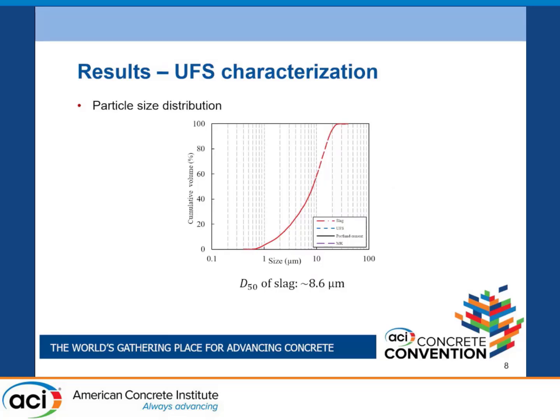Now I want to present the results for UFS characterization. For the slag before grinding, the particle size was around 9 micrometers, 8.6, and it decreased to 0.9 micrometer. For comparison, the mean particle size of Metakaolin and Portland cement was also similar to the slag, about 9 micrometers.